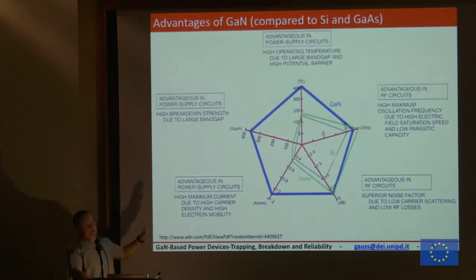So this is just an introduction slide. You have seen yesterday the reason why gallium nitride is very good, but this picture was not shown. So to me, it is important to show you why gallium nitride is good. If we look at this multi-axis plot, you see the maximum temperature, the high frequency, the noise figure, the high current level, and the high breakdown volts per micron. You see here the three major semiconductors: gallium nitride, gallium arsenide, and silicon. Silicon carbide can be closer to gallium nitride. In some aspects it is better in terms of high voltages, a little bit lower in terms of amps, but is similar to gallium nitride.